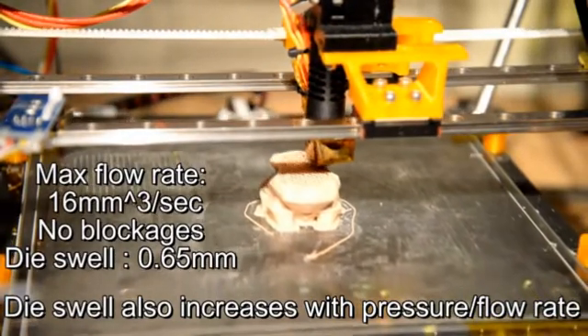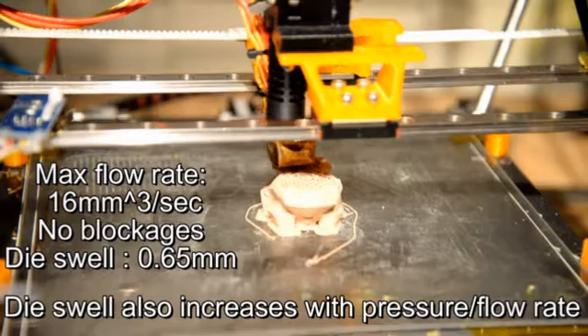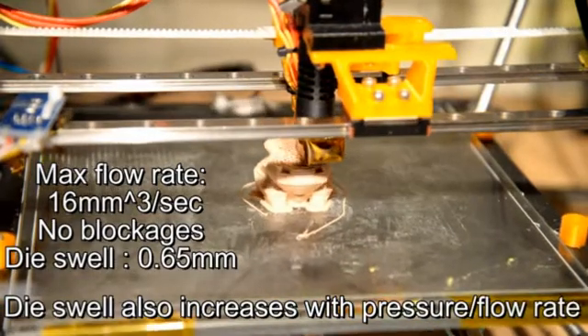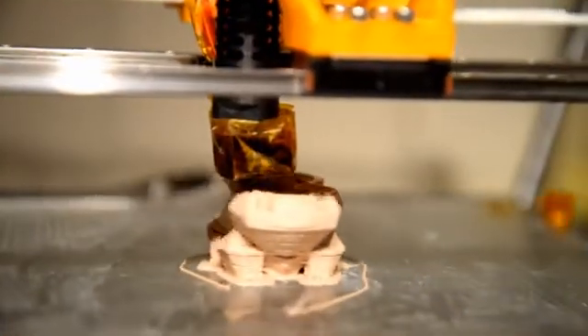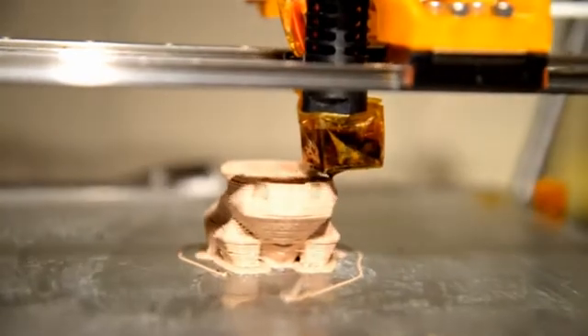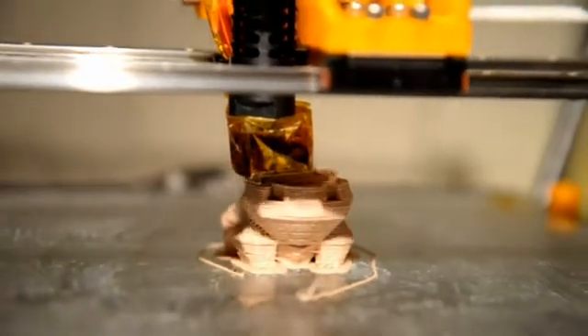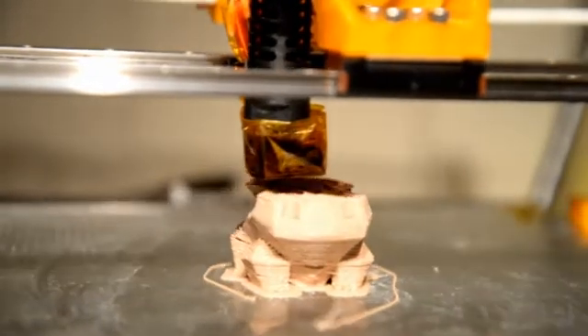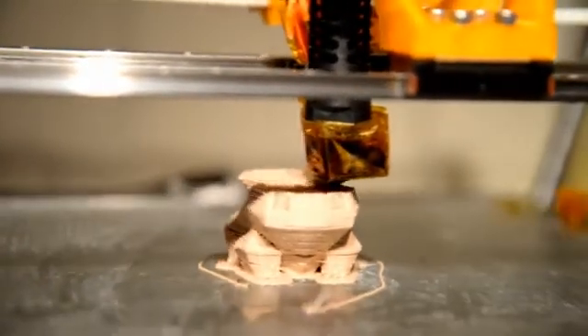So this is increased by extruding at a lower temperature, and hence there's more residual stress in the material as it's coming through the nozzle and you get more spring back. So I was able to get about 0.65 thick strands coming out of my extruder measured with a vernier, just with free air printing, and so that's where I started.